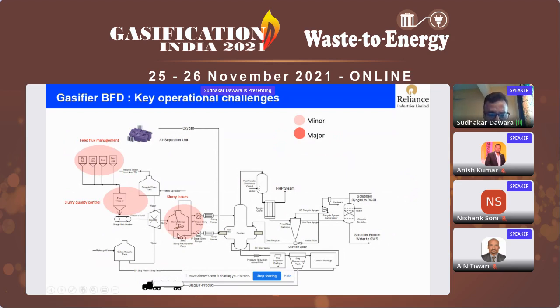We had a lot of issues in the storage tank. We needed to redesign the baffles. We needed to redesign the way we operate the agitator. So many things were done. Then, it's an entrained flow gasifier, as everybody knows, so many ash particles get entrained into the syngas, and we have deposition issues in the hot gas path in the second stage. And because we have gone for a syngas cooler design, not a total quench design, we have a lot of deposition issues in the syngas cooler.